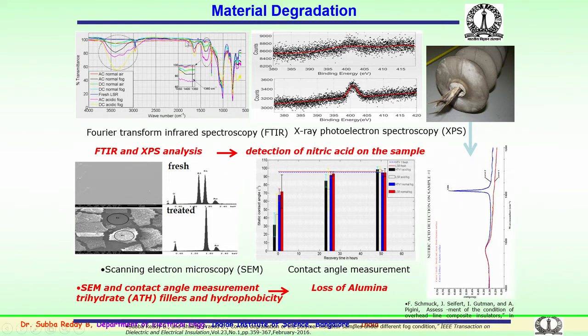The Fourier transform infrared spectroscopy gives the spectrum in this way, where very clearly there is a change which is very important for us here. This particular change happens at a wave number of 1350 to 1370, where it shows, depending upon the fog, either acidic or normal fog, the formation of nitric acid. The fog with the help of the corona activity leads to nitric acid. This is very dangerous in case this nitric acid formation enters the surface of the rubber insulator. Similar to that, there have been reports that brittle fracture could occur. This brittle fracture could be because of the formation of nitric acid, which could enter the surface inside the fiberglass rod, and the failure of the fiberglass rod could happen.